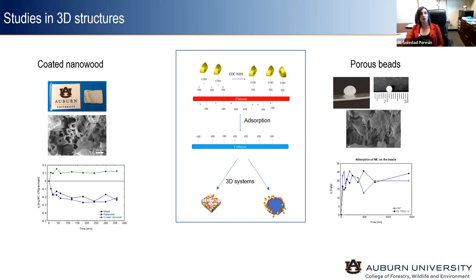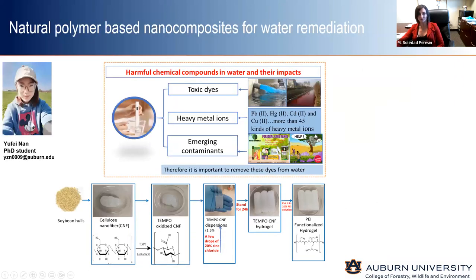And we assembled this into beads, and we assembled this as a coating for nanowoods. In both cases, we coated this cyclodextrin grafted onto chitosan onto the lignin-extracted aerogel or nanowood, and also onto these porous beads. We optimized the grafting of the cyclodextrin onto the chitosan, and then we proved that the coating material has a higher affinity towards the removal of microcystin. This is a seminal work that I use to move forward and continue investigating this, with a recently funded CAREER NSF award on the assembly of polysaccharides towards emerging contaminants removal.